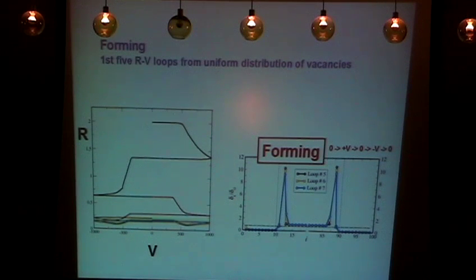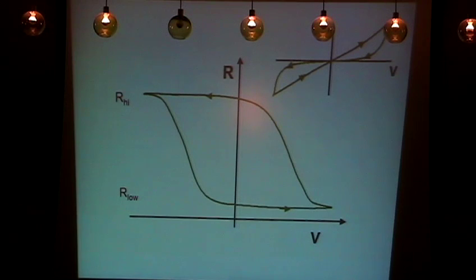So the system, in the language of Professor Chua, started at an initial state and got attracted in its basin of attraction to some dynamical state with a limit cycle, which now becomes repetitive. What we focus on is what happens during this cycle, where the system has already been formed and where the density of vacancy profile went from the trivial homogeneous one to this non-trivial one. And that happens because you get a periodic driving of the system. You change the driving, you may get a different type of response, but this is the driving that you get for the usual hysteresis loops.